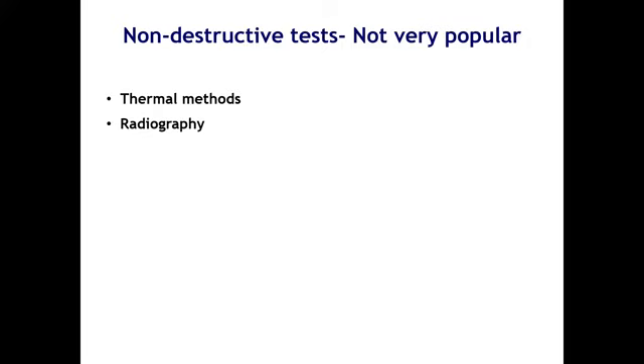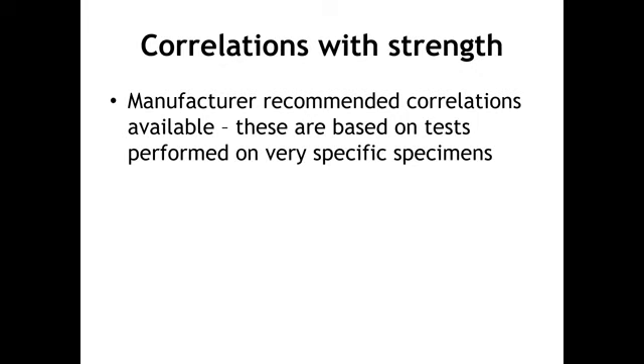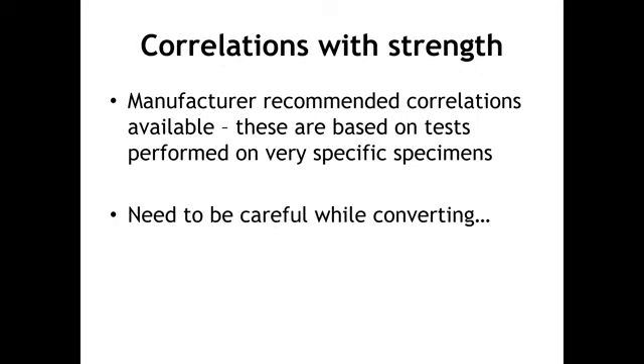As I said earlier, the carbonation of the surface produces very, very random numbers, and that number will not be able to decide anything at all. The manufacturer gives a graph where we'll be able to give a recommendation saying that you'll be able to predict it. But the thing is, it is only specific to that particular specimen, because our concrete grade and our concrete making system and our type of concrete is totally different from the graph which has been related to that. So we need to be very, very careful if you want to convert that. If you really want to do it, then you need to cast a number of cubes and then do the rebound hammer, and then take those data, and with those data probably you can predict it. Otherwise it is not advisable to do it with this graph.